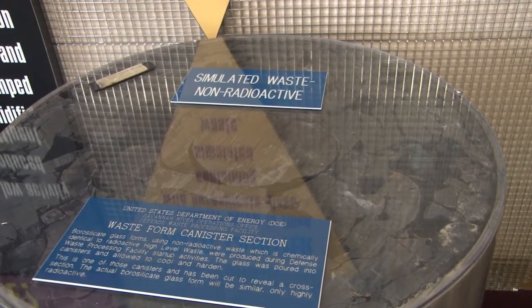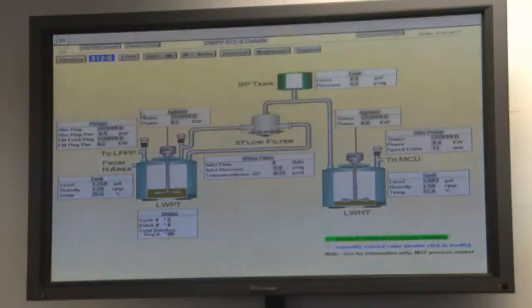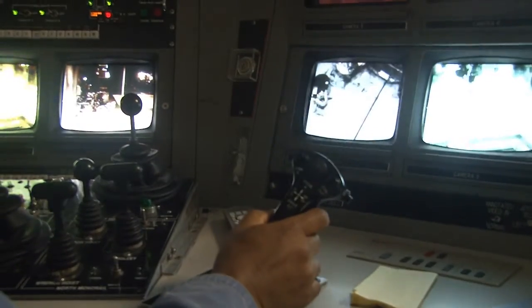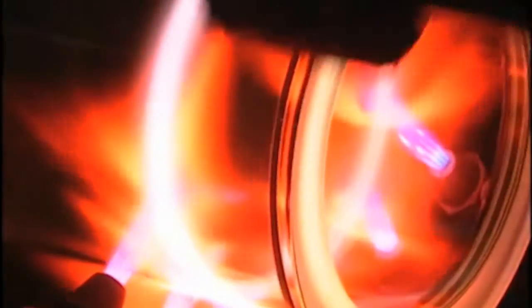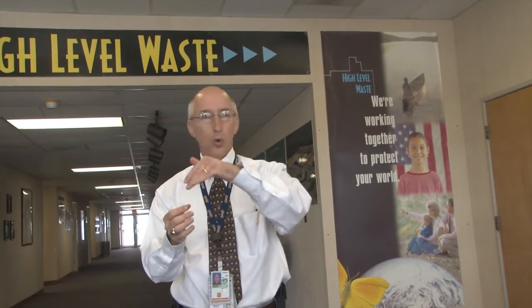The sludge is combined with other liquid industrial waste from the old and current nuclear weapons processes to create a slurry. This mixture must contain a specific level of radioactivity to be processed correctly in the Defense Waste Processing Facility. DWPF has a bunch of chemical parameters that have to be met to make good glass. Once the waste mixture is ready, 7,000-gallon mini-batches are sent to DWPF — only one or two transfers per week. At the facility, the waste is combined with borosilicate glass and sent to a 65-ton melter. The glass is poured into 10-foot by 2-foot canisters as a thin stream, and this takes an entire day.